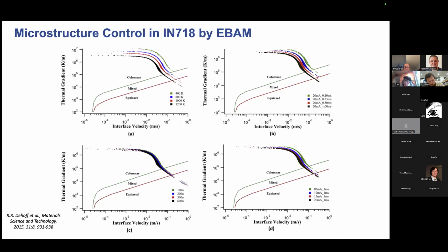So, with that in mind, this is some really nice work that came out of Ryan DeHoff and coworkers at Oak Ridge National Laboratory. This is microstructure control in Inconel 718 by electron beam additive manufacturing. Here you're looking at gradient versus velocity and this columnar to equiax transition, or CET. And here you're looking at the GV conditions that are experienced relative to the CET, which has a very big impact on the microstructure development and allows you to have some control over microstructure development during processing.